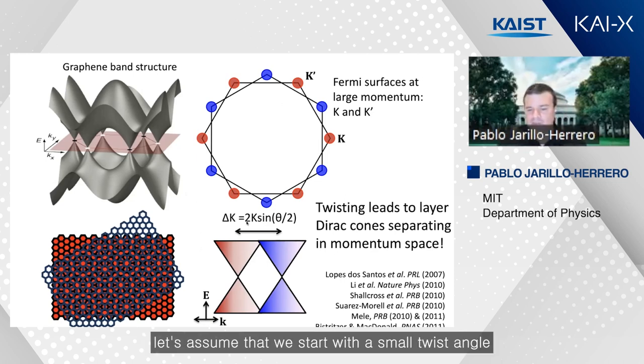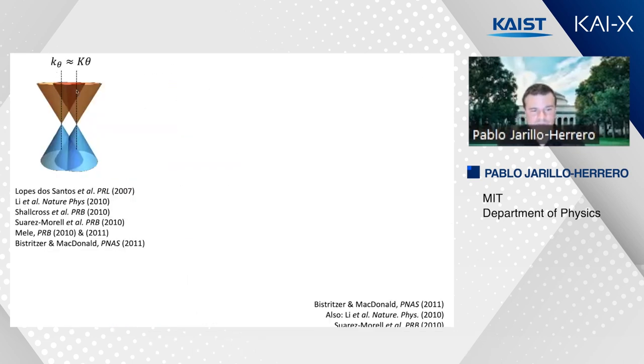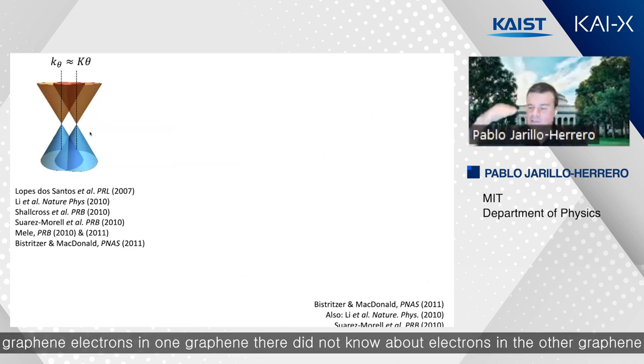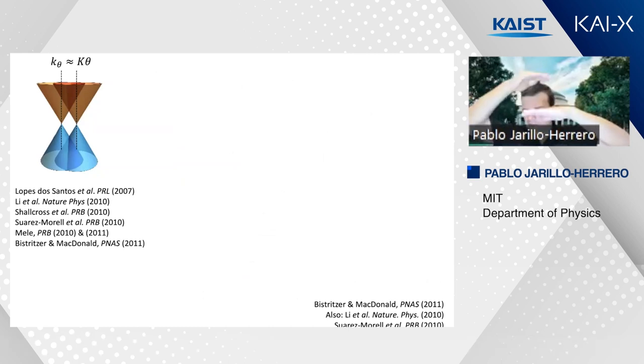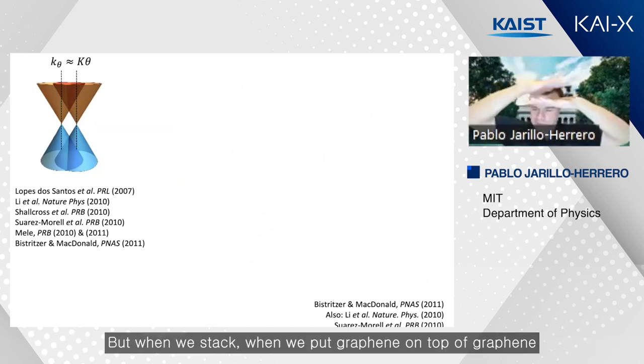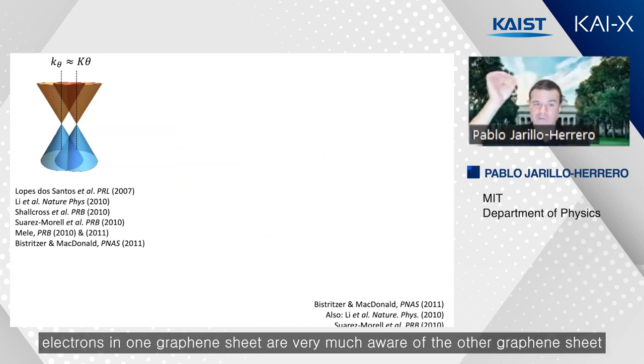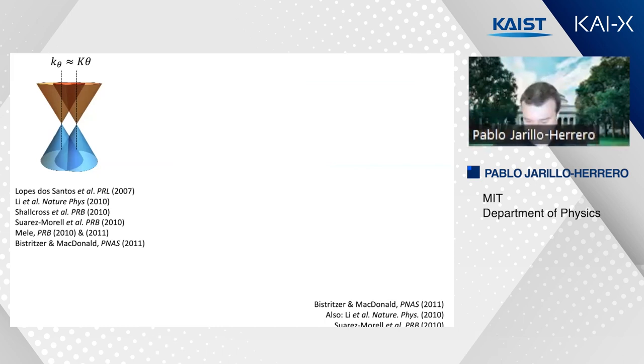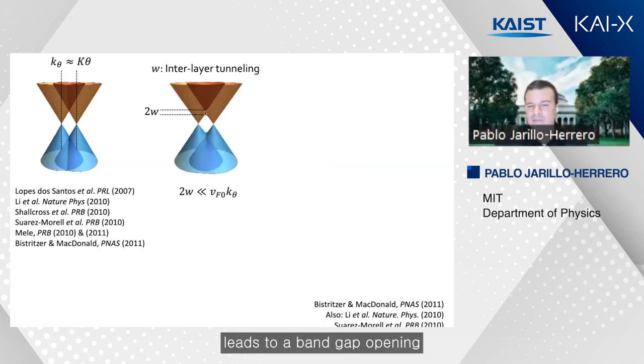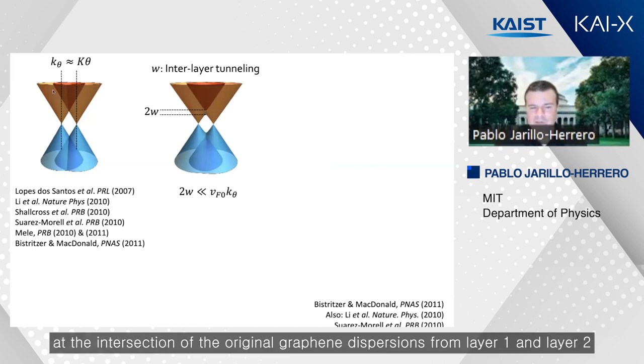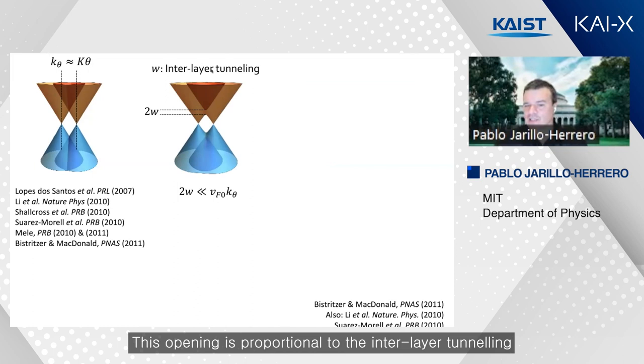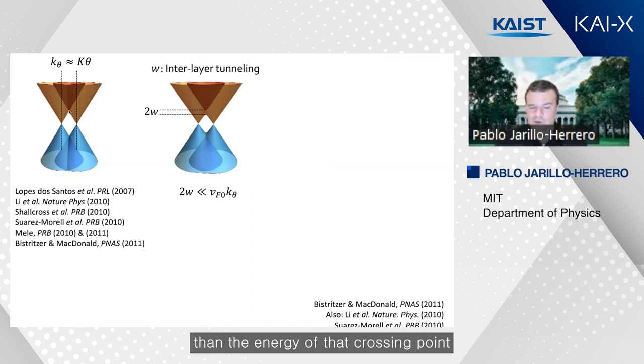Let's assume that we start with a small twist angle, so that the separation in momentum space is proportional to the angle. And let's see what happens to the electronic structure. This would be the situation if the electrons in one graphene layer did not know about the electrons in the other graphene layer. But when we put graphene on top of graphene, electrons in one graphene sheet are very much aware of the other graphene sheet. In particular, they can tunnel between the two sheets. That interlayer tunneling leads to a band gap opening at the intersection of the original graphene dispersions from layer one and layer two. This gap opening is proportional to the interlayer tunneling. This is the situation when the interlayer tunneling is much smaller than the energy of that crossing point.